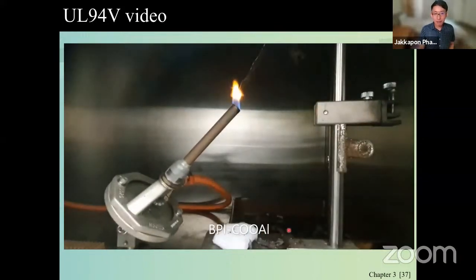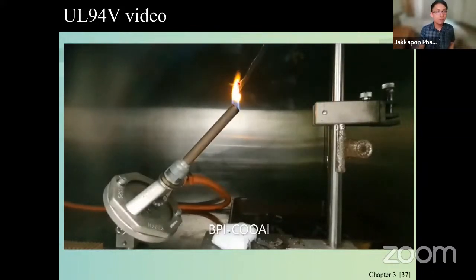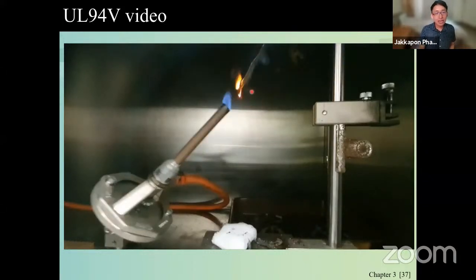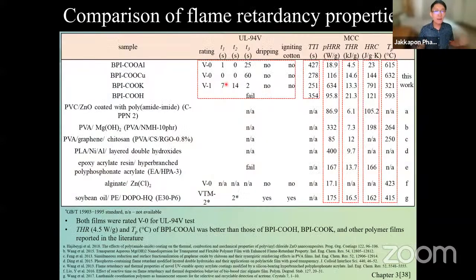But here is actually the best, aluminum. You see that when the fire is burning, the aluminum is protecting the layer of the polymer, and it's not really burning that fast. So here it's going to be the BPI-COOAl. This is the very best in this series. I'm going to tell you that the first biopolymer failed. The potassium one is not very good. There's no dripping or cotton ignition, but the aluminum one is actually sustaining very well. It has V0 for the rating. V0 is actually the best rating for this.